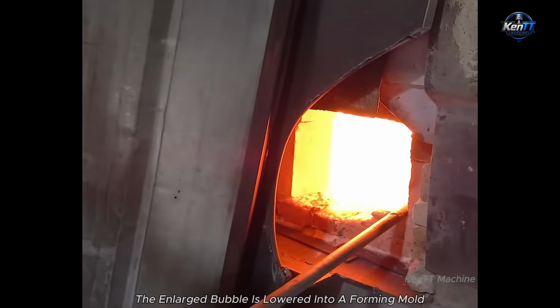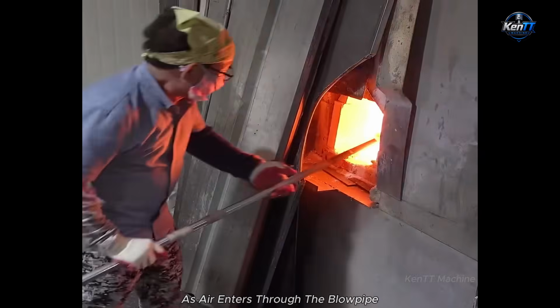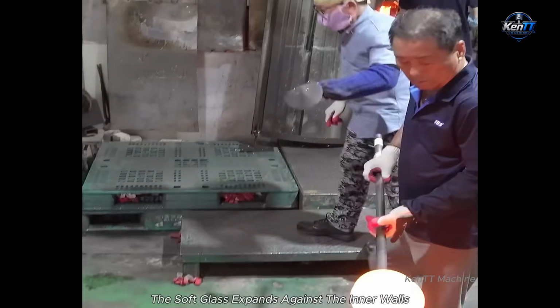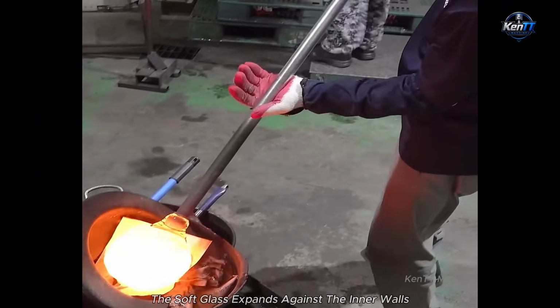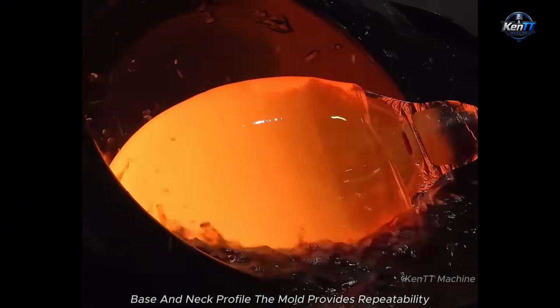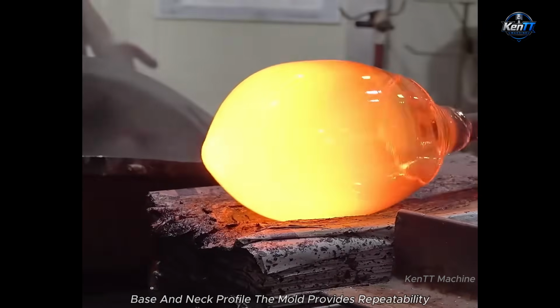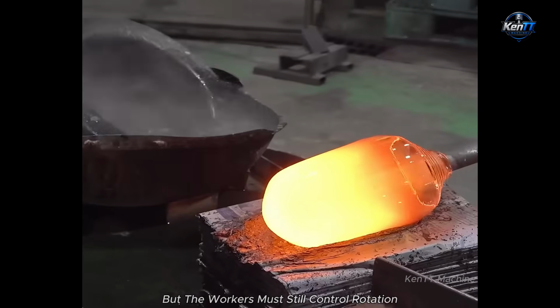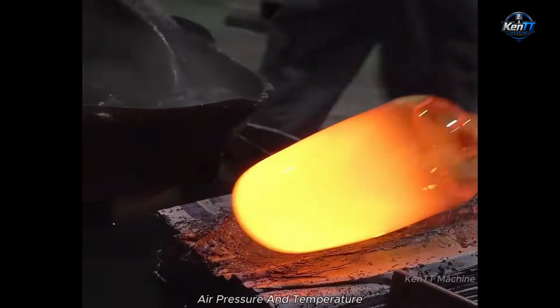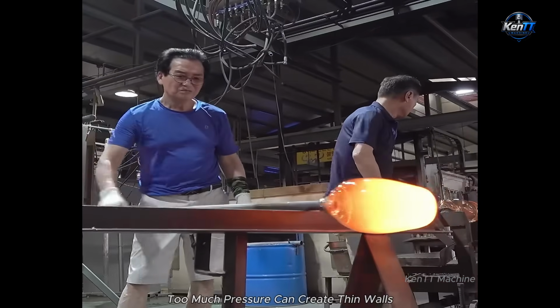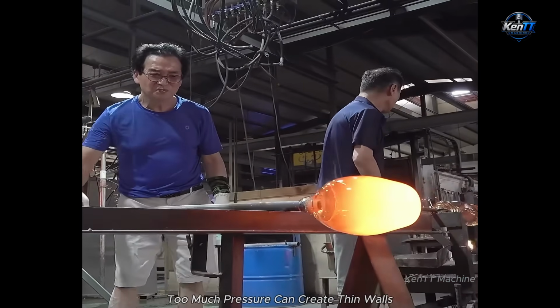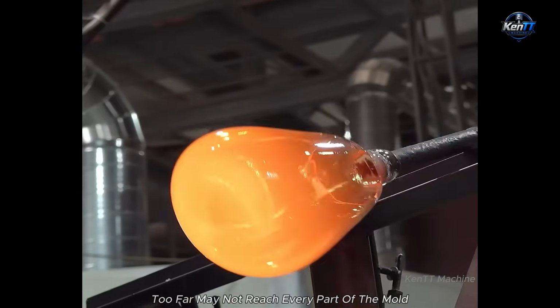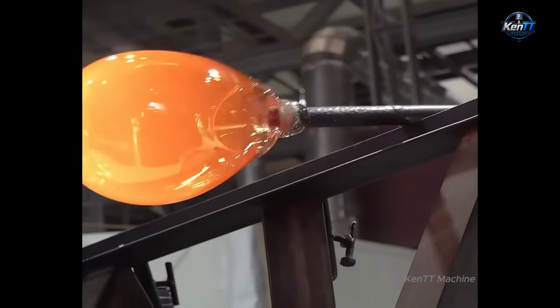The enlarged bubble is lowered into a forming mold. As air enters through the blowpipe, the soft glass expands against the inner walls and adopts the required diameter, base, and neck profile. The mold provides repeatability, but the workers must still control rotation, air pressure, and temperature. Too much pressure can create thin walls, while glass that is cooled too far may not reach every part of the mold.